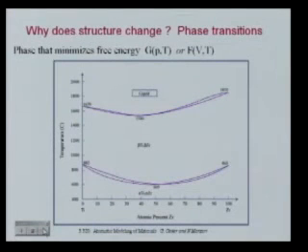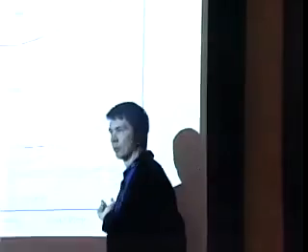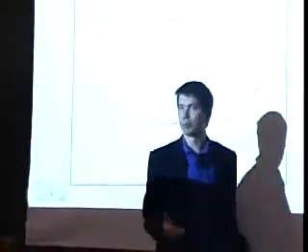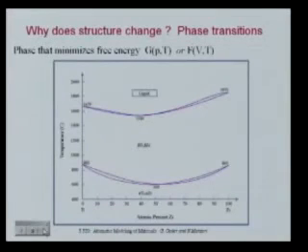Okay. So that was the example of thermal expansion. So there you had to worry about phonons, maybe electrons. Here's another example where you would absolutely need a temperature-dependent study. Here's the phase diagram of titanium zirconium. Titanium and zirconium are both hexagonal close-packed, HCP, at low temperature. At high temperature, they're both BCC. This is the transition temperature on the titanium side. This is the transition temperature on the zirconium side. Let's say you wanted to be able to predict such transition temperatures. Then you obviously need to get the subtle energy difference between HCP titanium and BCC titanium as a function of temperature. So you need to know what contributes to the entropy of these phases.